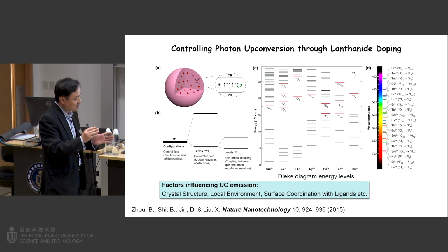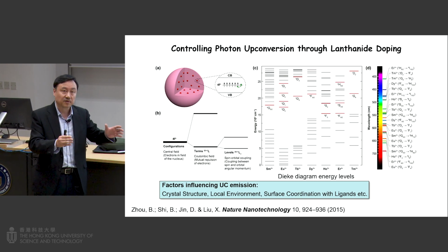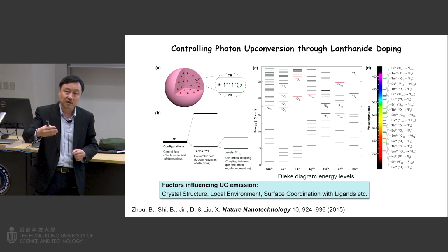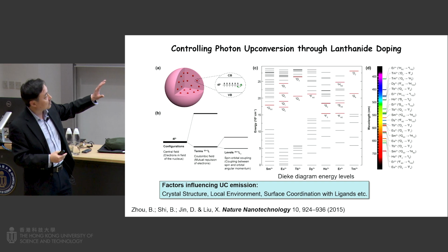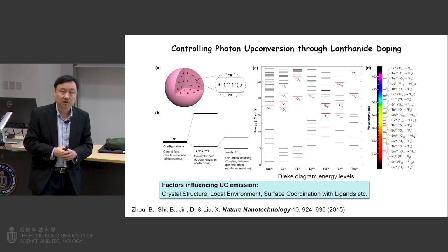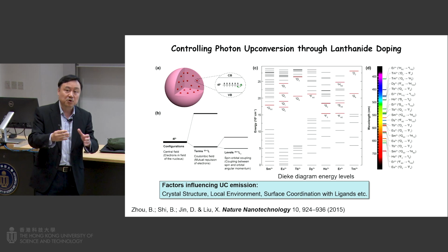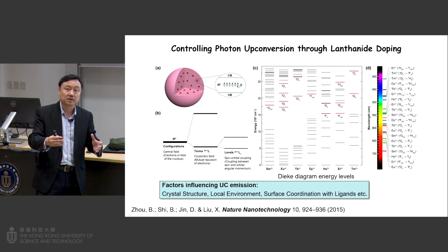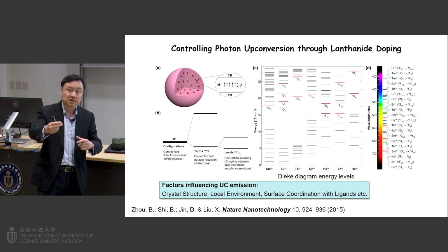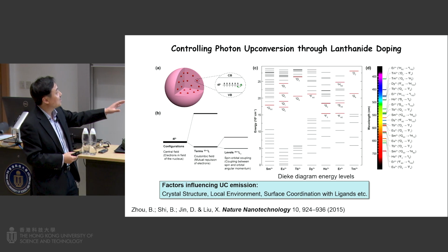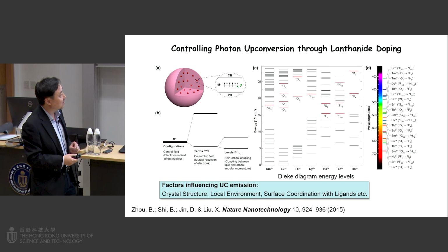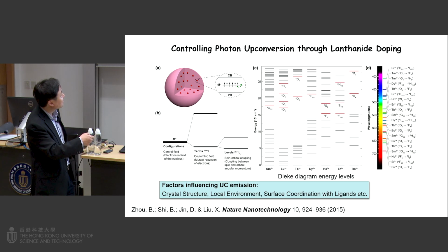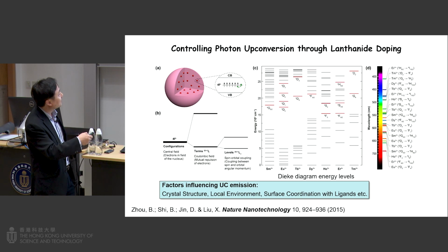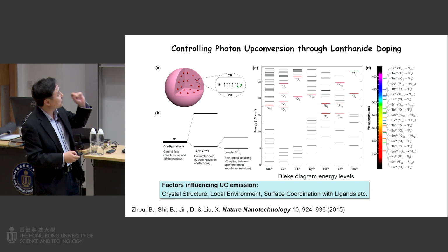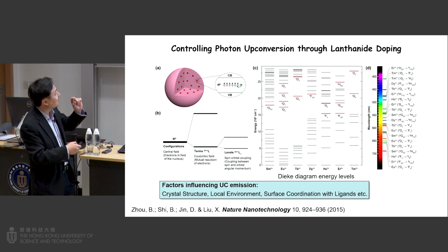Their behaviors are quite similar in terms of emission and labeling potential, but they are quite a different class of materials in terms of the emission mechanism. It is very different from quantum dots, which rely on the quantum confinement effect. For lanthanide-doped particles, the emission comes from the emitters, basically the lanthanide dopants within the host matrix. So it is because of this lanthanide dopant emission.